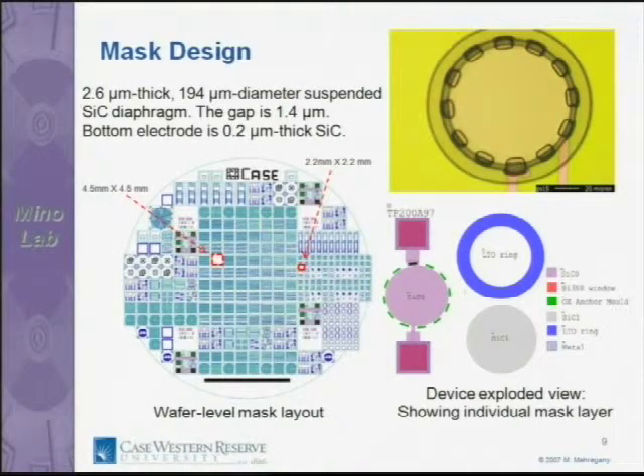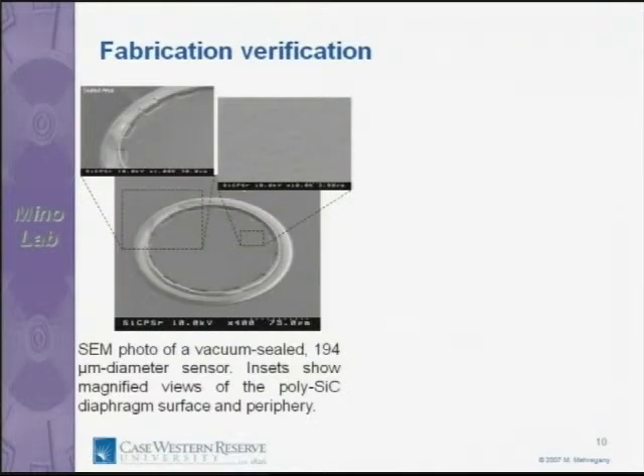The cavity underneath the diaphragm is initially a silicon dioxide film, and then later on it's etched through these holes. Once the cavity is etched and the diaphragm is freestanding, we seal the edge with this ring and create the sealed cavity. Just to show you some SEM photos of these sensors. Here the seal that seals the cavity. Here is the diaphragm. These are the holes through which the silicon dioxide under the diaphragm was dissolved to free up the diaphragm. You can see a magnified view of the surface of the film.